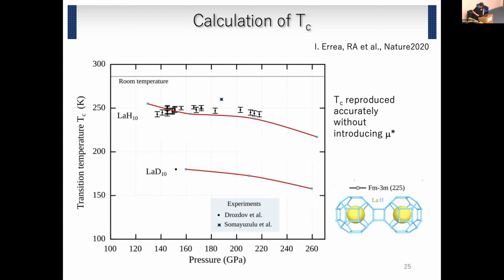And for me, it seems that it's not an accidental coincidence. In quite a reasonable range of pressure, the symmetric structure, which is good for superconductivity, is stabilized. And if we calculate TC, it gives a value very close to the experimental value. Of course, I will not say too strongly about that. We introduced a static approximation and our calculation is based on the Migdal approximation. But still, this result is important and interesting.